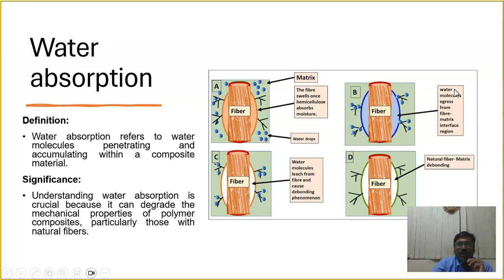The second one is that water molecules egress from the fiber-matrix interface region. After a certain period of time, the water may be released from the fiber content to the matrix region, where the fiber and the matrices are covalently joined together. So the water molecules leach from the fiber and cause debonding. When it is leaching from the fibers, it creates debonding due to the internal stress developed by the moisture present between the regions. Then the natural fiber and matrices debond. So these are the various phenomena because of water absorption.